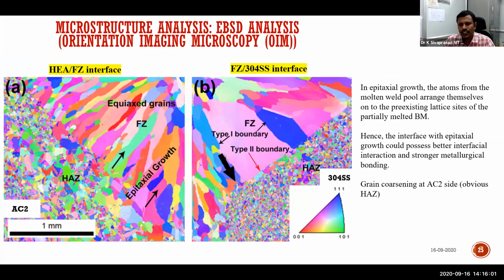Then at the fusion zone also we decided to go for texture based or orientation based microstructure analysis, and to our surprise we have seen that there are type 2 boundaries which evolved here. Type 2 boundaries normally evolve with a butter layer, whereas in this case the extreme wide variation in chemistry associated with the system has started evolving type 2 boundaries. And on the HEA side we have seen an epitaxial kind of growth, almost matching boundary sizes with the orientation matching from both the HAZ side as well as the fusion zone side. So that's called epitaxially grown crystals.